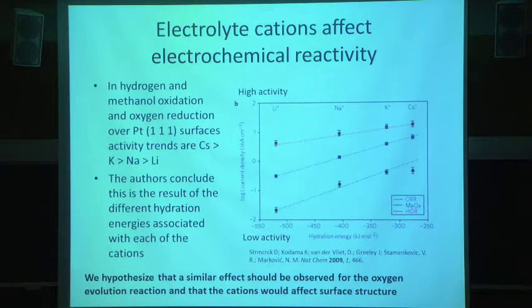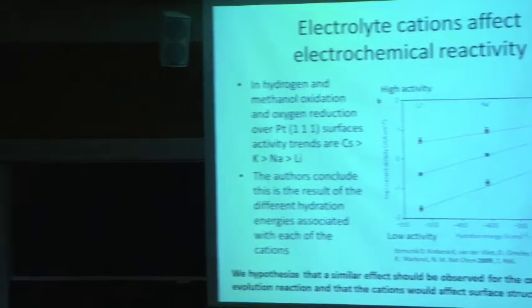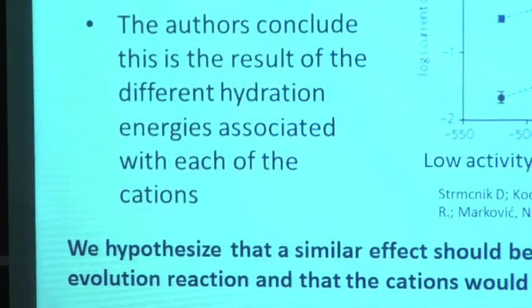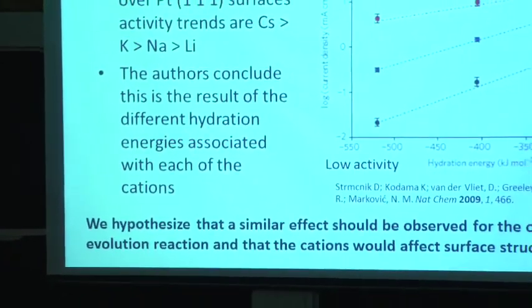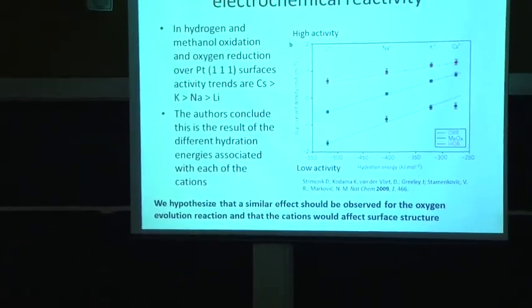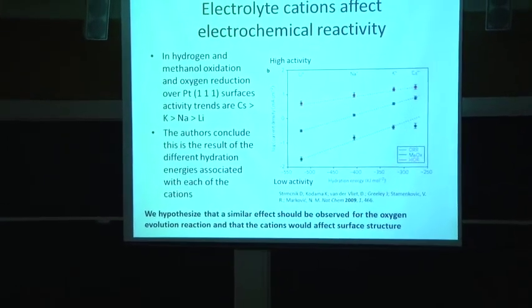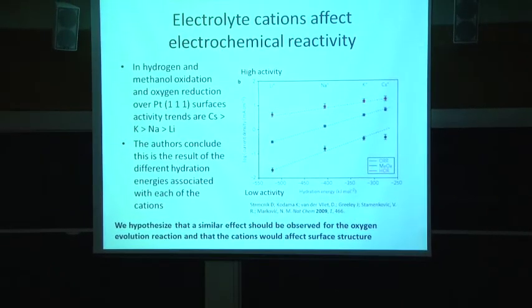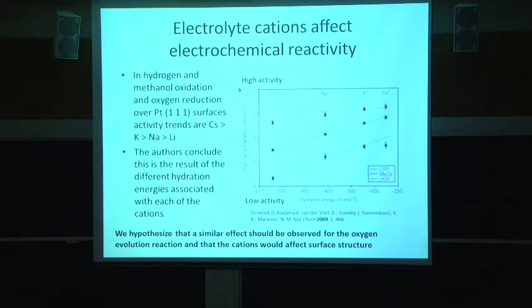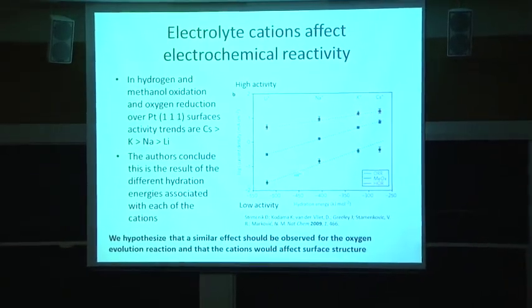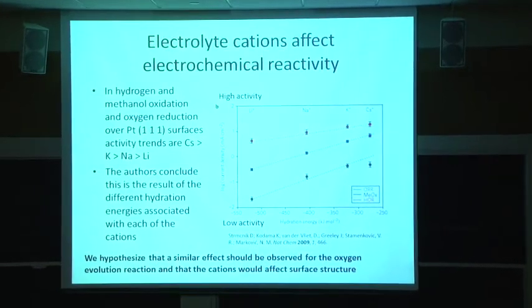So we started thinking about this, and we were inspired by a paper in Nature Chemistry that talked about electrolyte cations affecting electrochemical reactivity. This group showed that methanol oxidation, hydrogen oxidation, and oxygen reduction all occur on metallic surfaces, right? But they ran them in different electrolytes, cesium, potassium, sodium, and lithium hydroxide, and they saw very big changes in the electrochemical reactivity. Lithium showed the worst activity, cesium showed the highest activity in almost every case. So it's exactly the same reaction, exactly the same metal surface. All they're doing is changing the electrolyte. And they're changing it in a way that they're not just messing with the pH or doing anything that would be obvious. This is the log of current, right? So an order of magnitude change in the current just by changing the electrolyte. And so we were really interested in this.